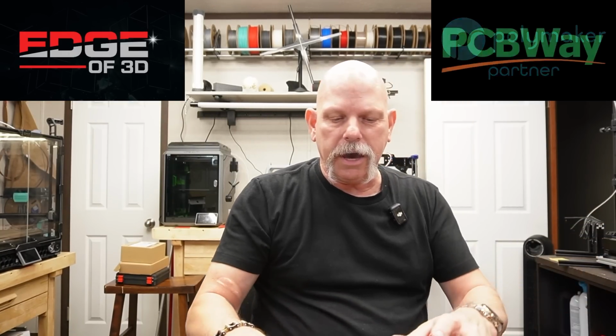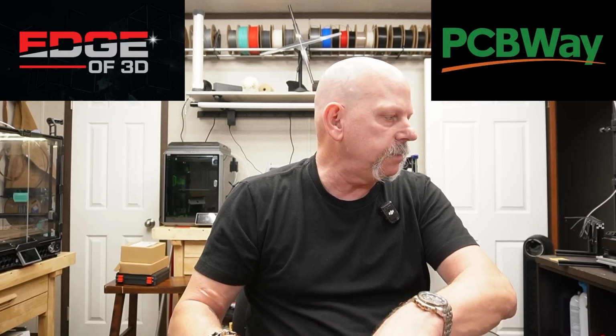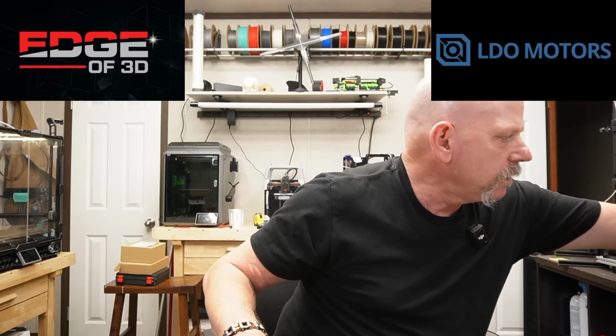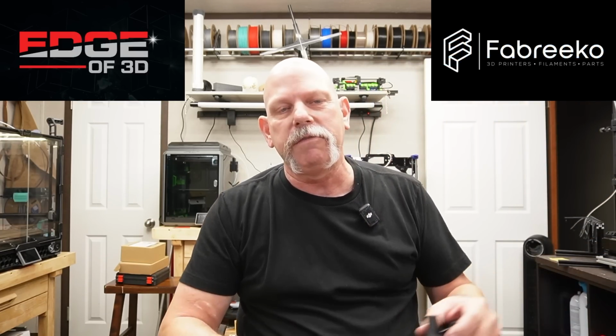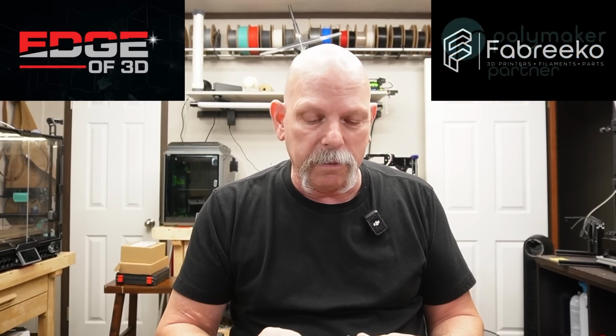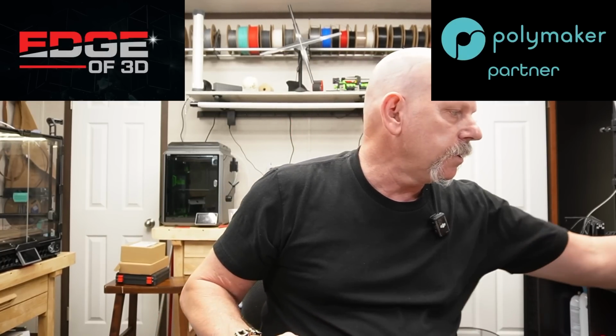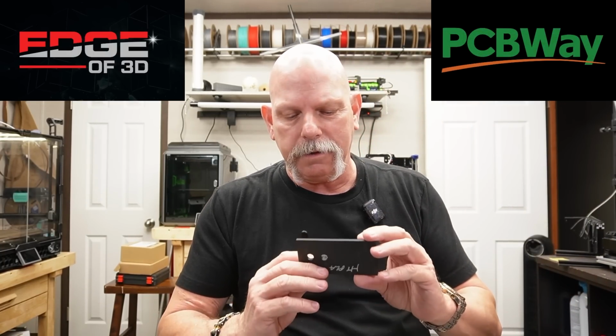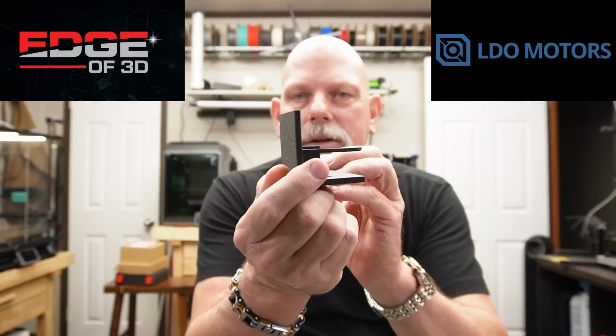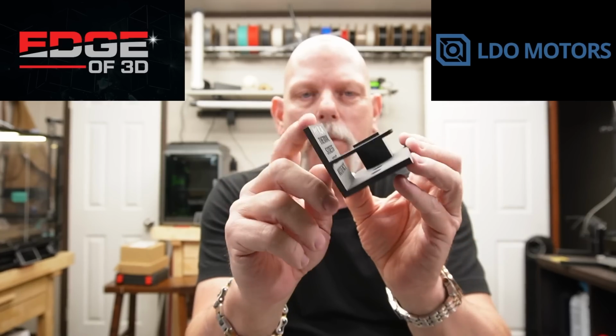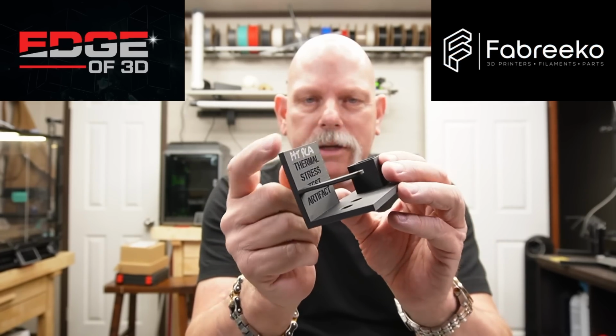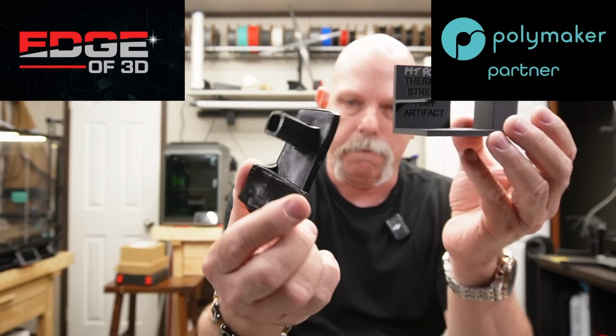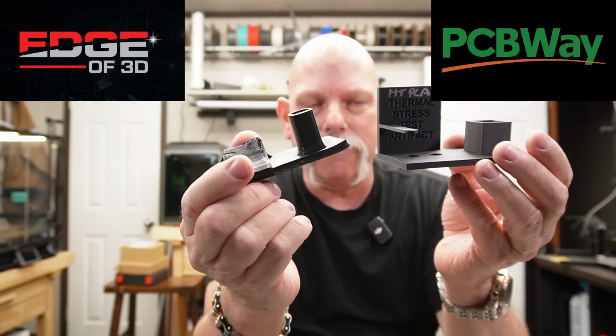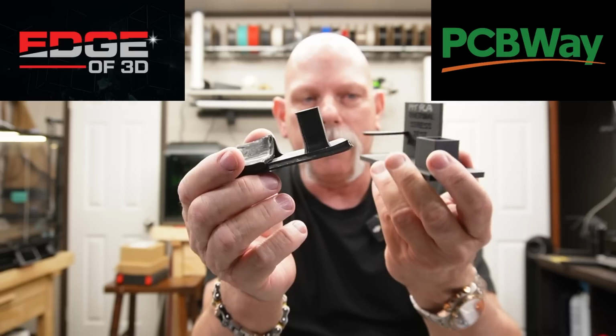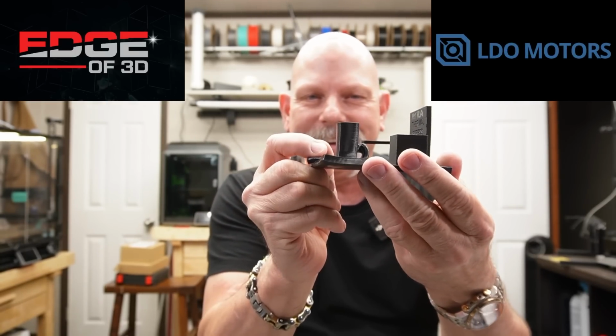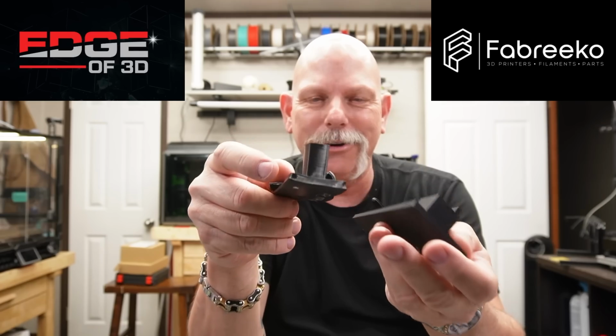So now let's look at the artifacts tests. And let's look at the PC Max first. I only did 4 of these. I should have done a whole bunch more, but I only did 4. And so I'm going to use the High Temp PLA as the model because this is what it's supposed to look like and what it did look like when it was first printed. This is PC Max after being in there at 150 degrees. It grew. As you can see, it grew.